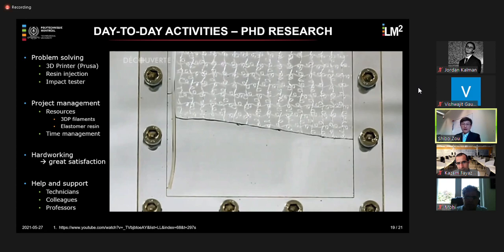So at the time that I ordered this elastomer, I made a mistake. That's the one thing that I wish I knew during my PhD, so I could save time. After ordering the high refractive index elastomer, I thought that because I have to wait 6 months, maybe I can try to synthesize the elastomer myself. So I invested a lot of time in the chemical synthesis of the high refractive index elastomer, because I found some literature where they were able to synthesize this elastomer with a high refractive index, which is very similar to my PC fiber, and that's exactly what I want. So I followed their protocol to make this.